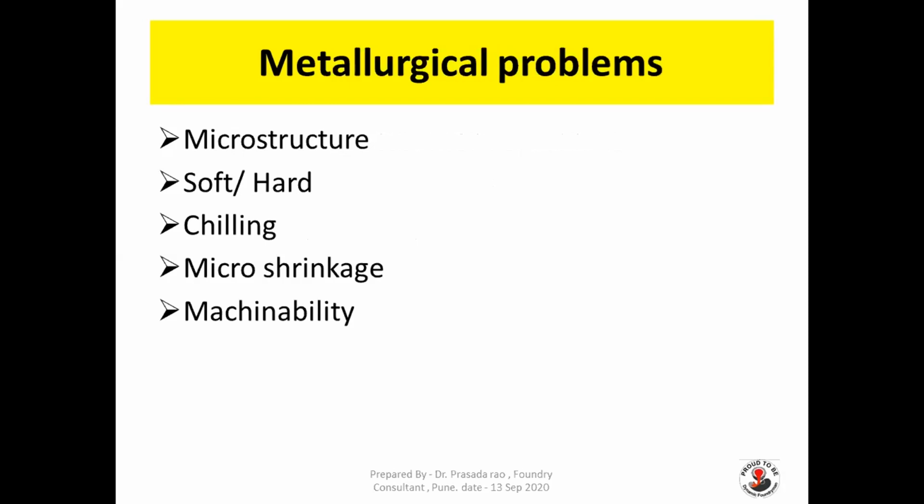And you see, we talk more about inoculation, and many suppliers talked about inoculation earlier. Now they are not talking. I will talk about one thing. People were using cupola, and I know many foundries hardly add any inoculation. Even if they add very bare minimum, they still produce good castings. Why? The inoculation effect is coming in the charge mix. It is coming in the cupola itself. So there we don't talk about inoculation. When you come to induction furnace, we talk about inoculation. So inoculation has become more important since induction furnaces have come.